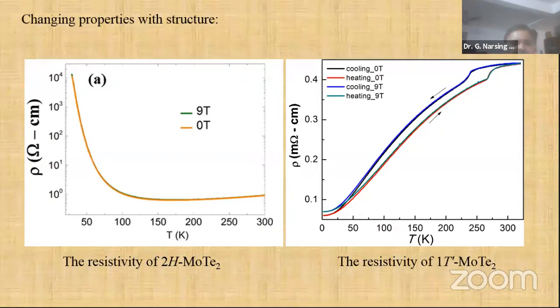So this is the resistivity of molybdenum telluride in the hexagonal phase. This is a semiconducting or insulating semiconducting behavior. With our instrument we measure at 0 Tesla and 9 Tesla also, to see whether any changes occur. Nowadays this type of study is common, because at low temperature and higher field, oscillations will come. For that purpose, whenever we keep a sample in the PPMS, we check all types of things.